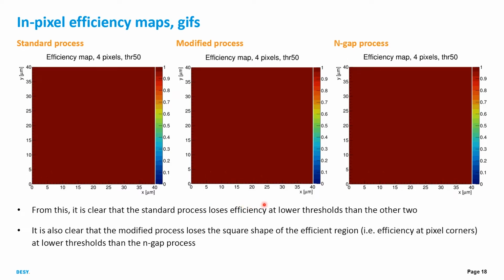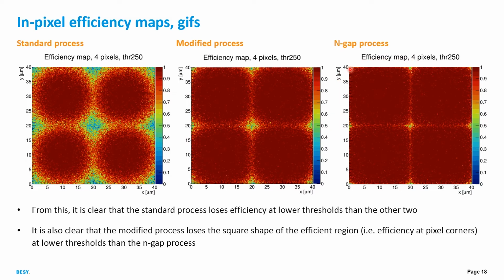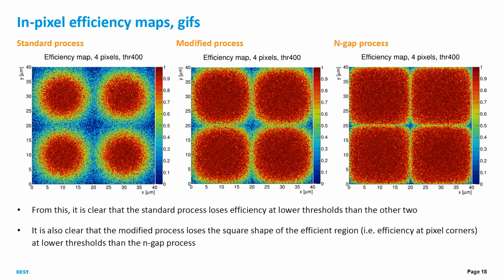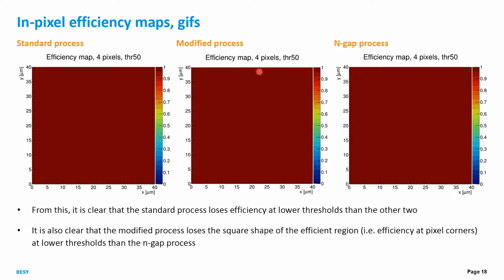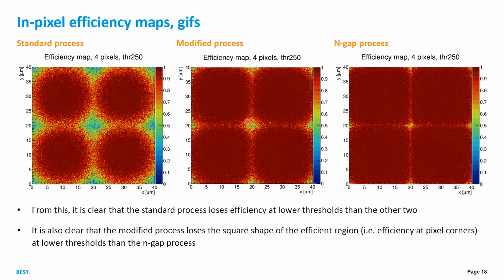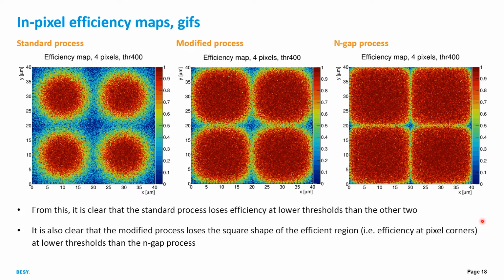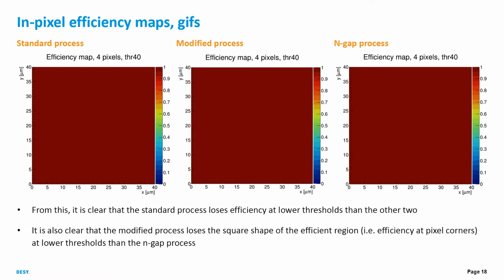Now, if we compare the modified process to the NGAP, we can see that this sort of square shape of the efficient region lasts for longer in the NGAP process, and this means that the modified process loses efficiency at pixel corners earlier than the NGAP process does, basically. So again, NGAP process is more efficient. This is just another way of showing it.